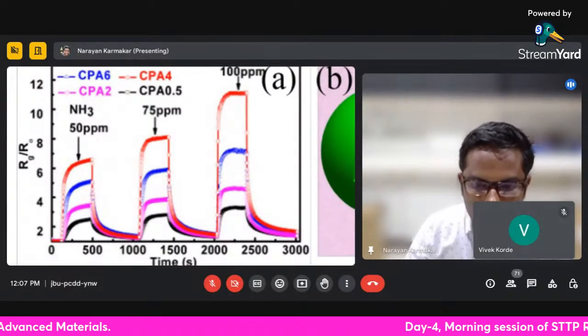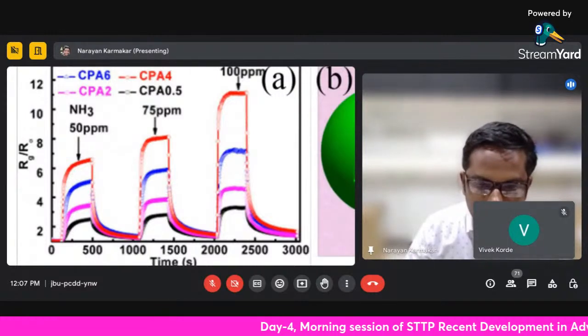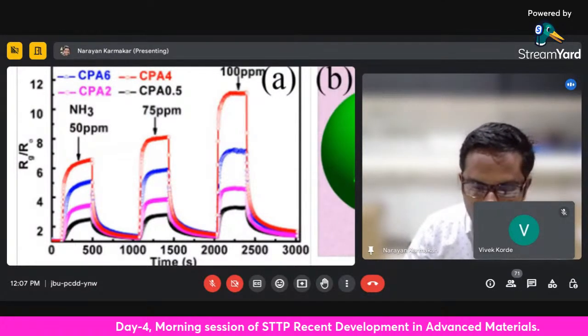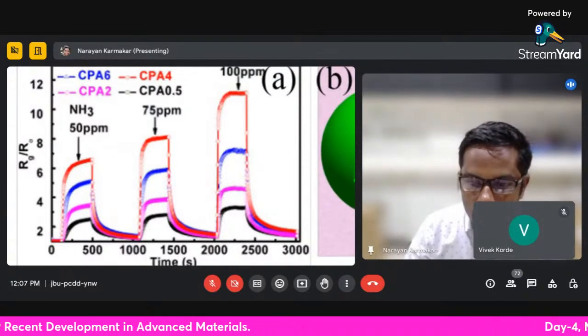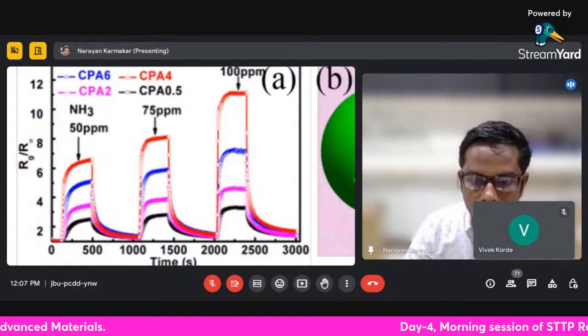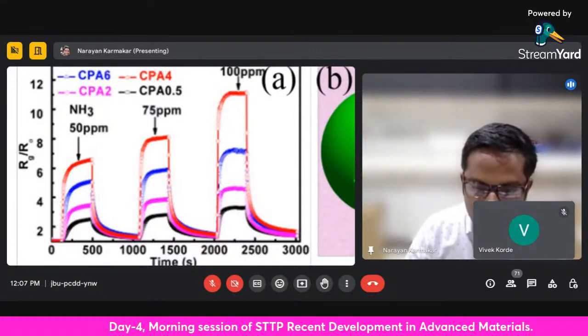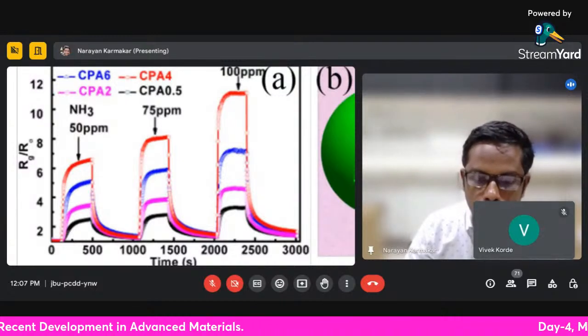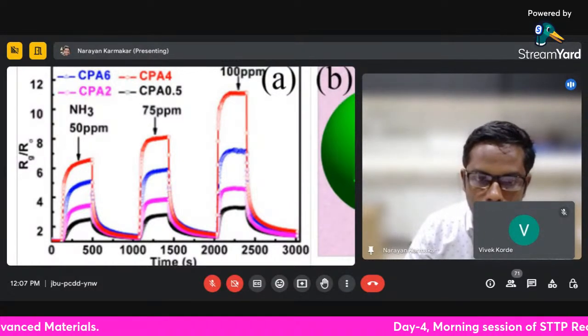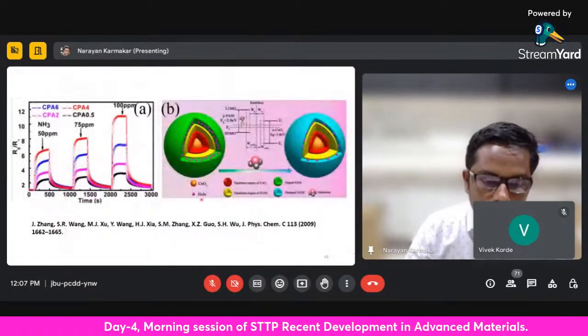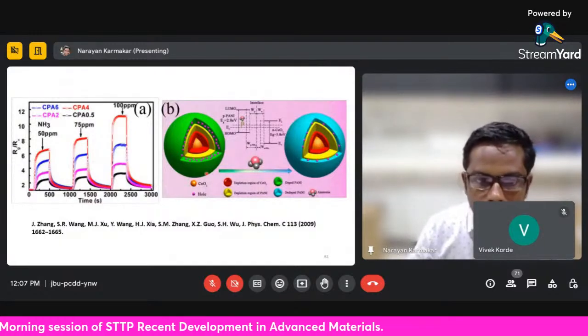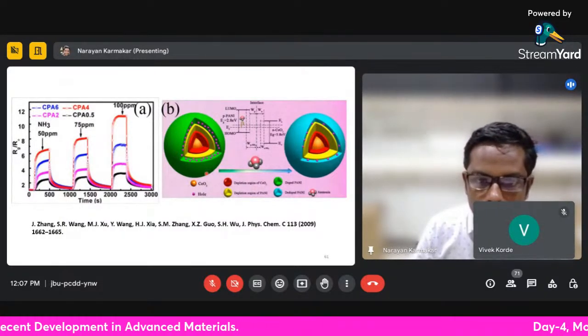Why? Because they concluded that a thicker shell thickness reduces the ammonia diffusion. If the thickness of the shell is very large, because of this thicker shell, the diffusion of ammonia decreases, and because of that it results in a low sensing response. Whereas a thinner Pani shell of the core-shell structure causes lower residual holes for ammonia interaction. So when designing the composite, we need to optimize the thickness of this Pani nanocomposite with the nanoparticles. This is one more example that we discussed.